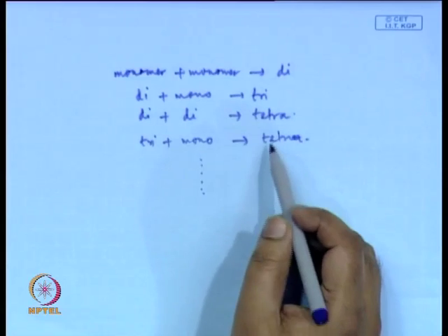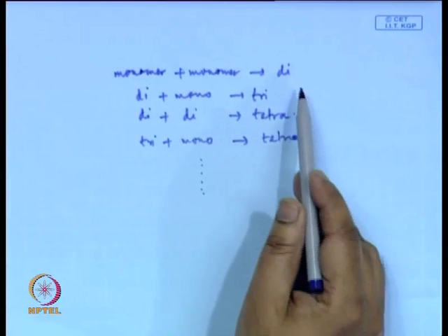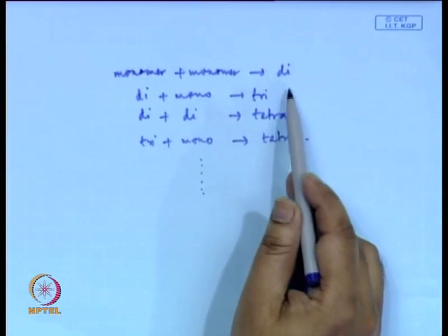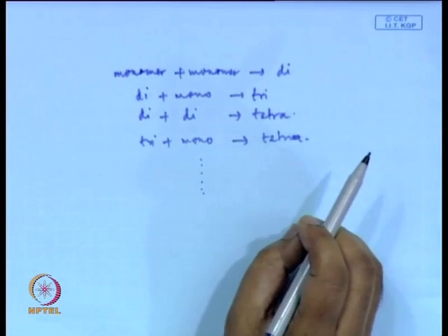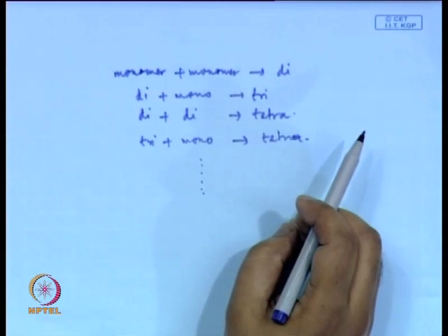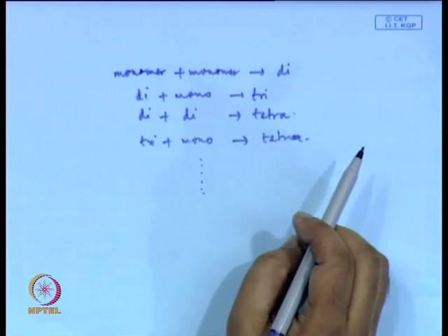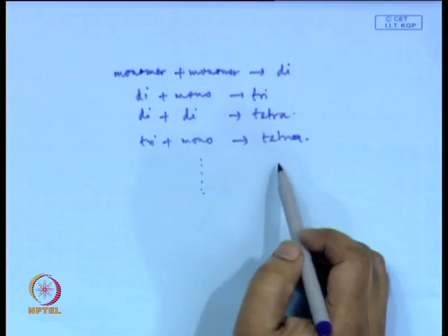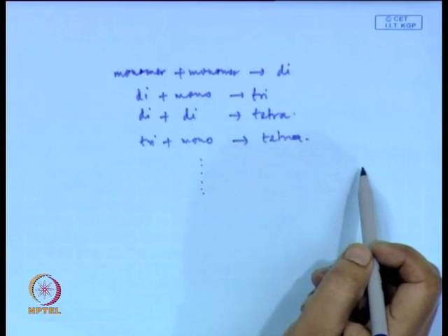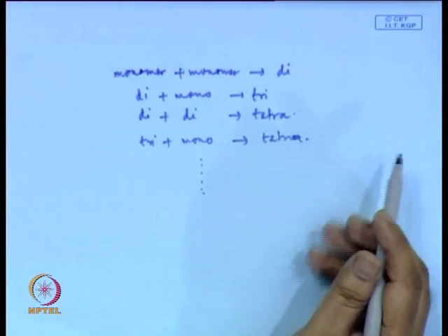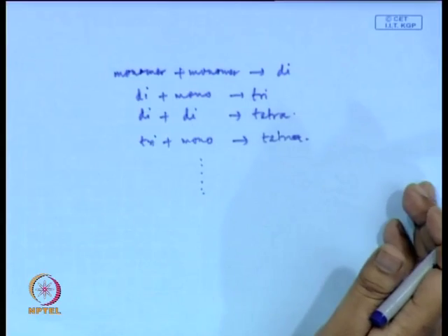In step growth polymerization, if you stop in between, you will see small molecules called oligomers and a small amount of monomer. The high molecular weight polymers in step growth only form at the very late stage of the polymerization process.